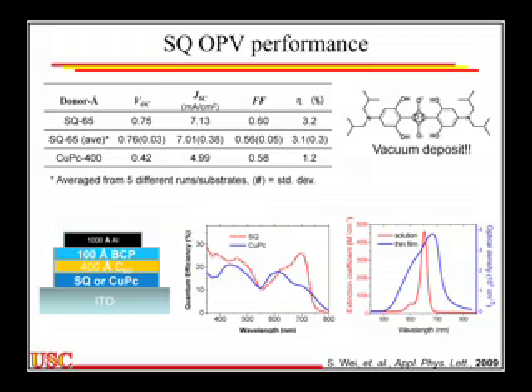If we play the games right, we can get a little bit thicker and do better than the 3.2% that I'm showing you here. But there is a problem with resistivity. This is an amorphous film. If you notice, the fill factor is dropping. We go from 0.6 down to 0.5, and that's because as we make the film thicker, series resistance goes up and the fill factor drops off. So if this is an amorphous film, crystalline films have better conductivity, both carrier conductivity and exciton conductivity and mobility.